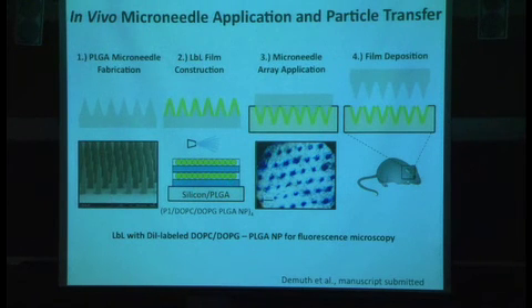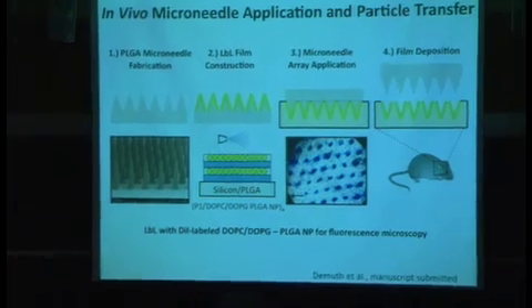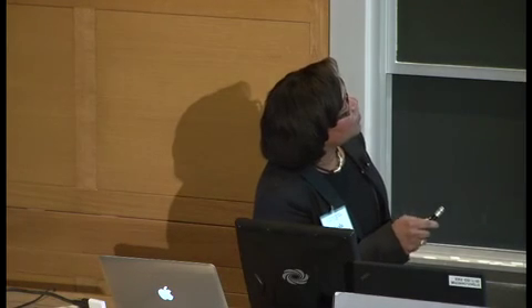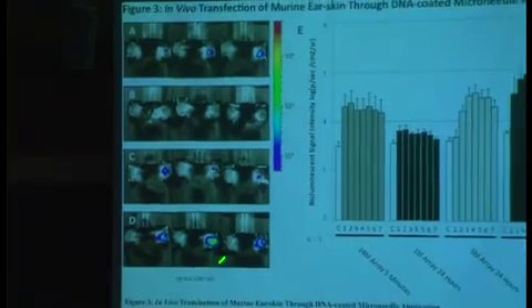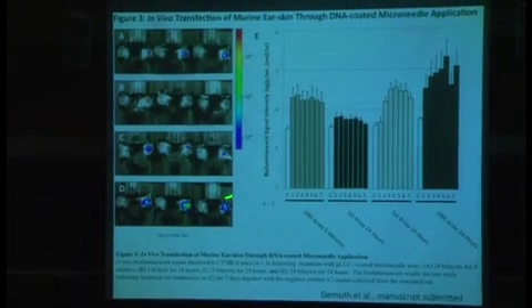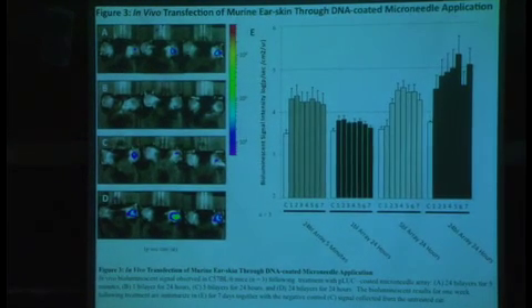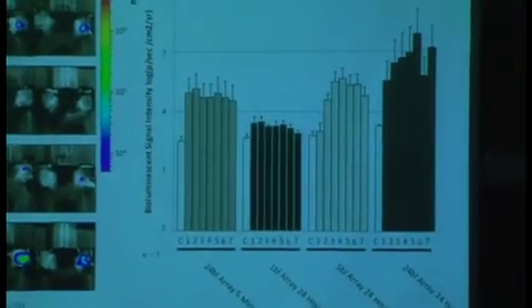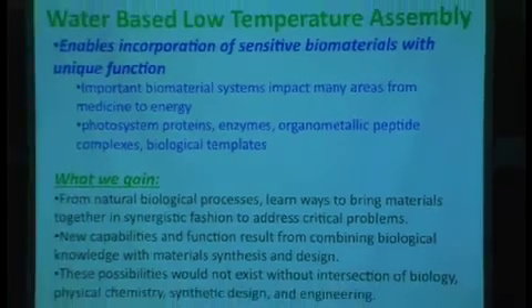And these films were released based on the choice of poly-beta-amino ester that we use, which determines the rate of release and the rate of degradation of these PLG nanoparticles. In this case, the nanoparticles contain DNA, and we use transfection of the luciferase gene to determine the efficacy of that transfection. At the top, you see our 24 bilayer film at 5 minutes. Then we have a 24-hour series in which we look at 1 bilayer, 5 bilayers, and 24 bilayers. So we're seeing dose dependence, and we see very strong transfection of these systems. In fact, they give us better transfection than a range of other very simple transfection agents.